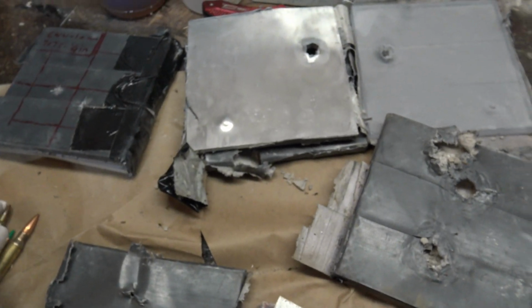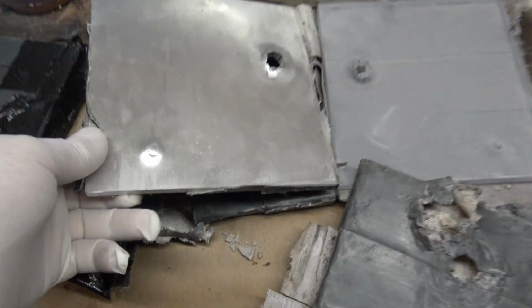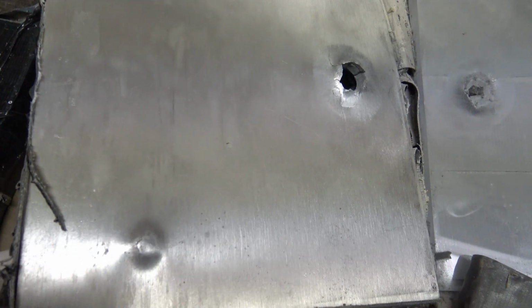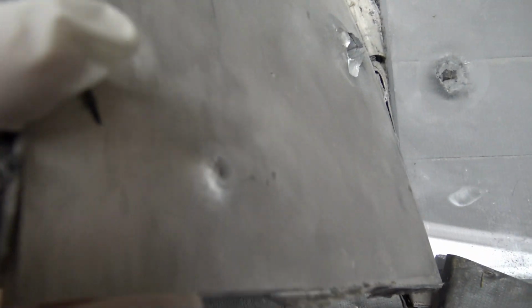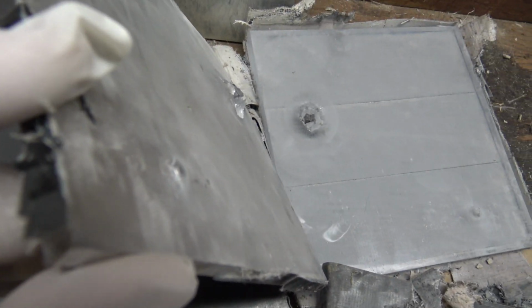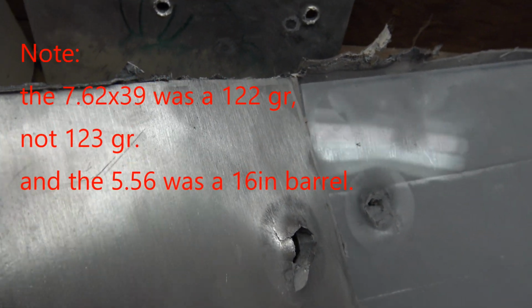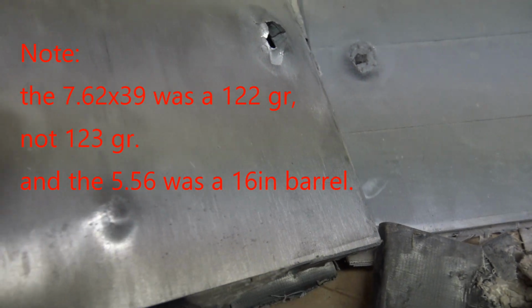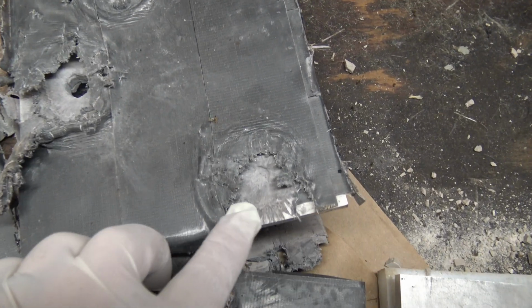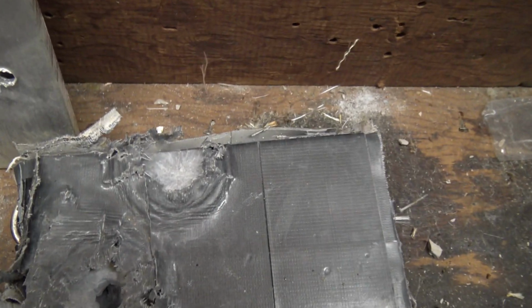First up, both a 122 grain Full Metal Jacket 7.62 by 39 and a 55 grain Full Metal Jacket 5.56 will stop on the 70-75 if it has an 8 to 10 millimeter porcelain strike face, leaving just a dimple with some cracks in the back of the 70-75.